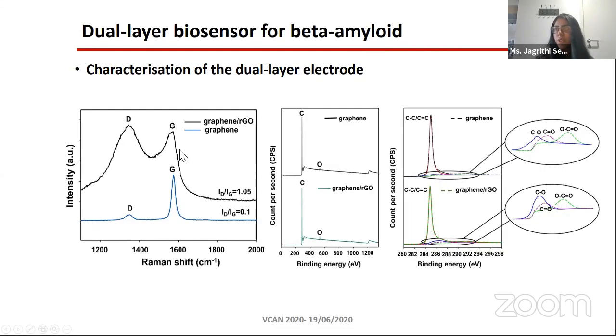This is the characterization results of our dual layer electrode. The first one is the Raman spectra. If we look at the Raman spectra of graphene, it's a very standard, very generic Raman spectra of graphene. If we calculate the ID over IG ratio, the intensity of D over G, that came out to be 0.1. And for graphene RGO, it came out to be 1.05, which is usually very common for RGO and graphene structures.